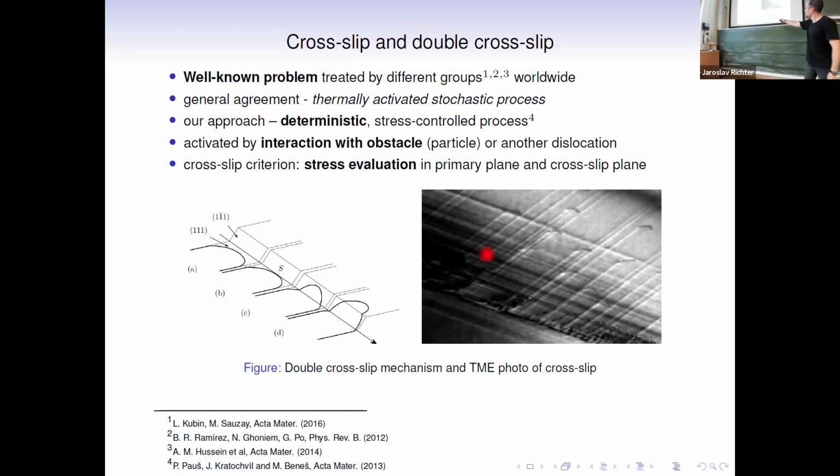Here, this cross slip, you can look at the right picture. Again, some TEM photo of the cross slipping. Is it a mechanism which includes a kind of 3D motion? So here you've got a family of crystallographic planes, and when certain conditions are met, the dislocation skips to something intermediate, which is called a cross-slip plane.